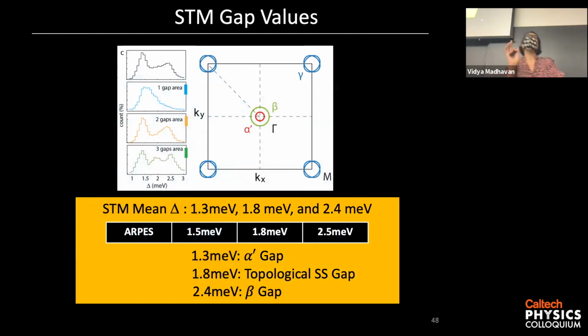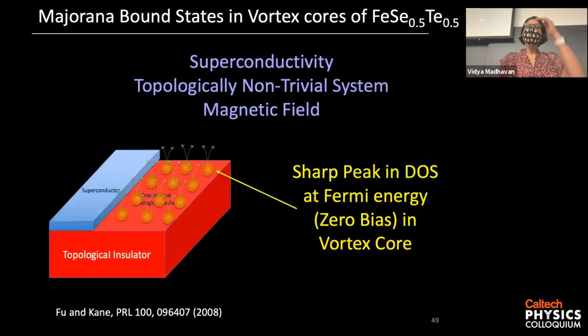And then you can compare. We have a huge amount of statistics. We can go to every point on the sample and measure the gap. And so if you compare statistically our gap magnitudes with what was seen by angle resolved photoemission, basically our numbers match really well. So from all this, all I want to tell you is that it does look from our data that there is indeed a new gap associated with this special surface state.